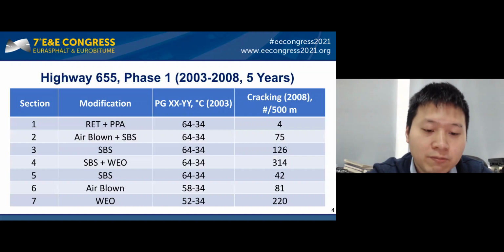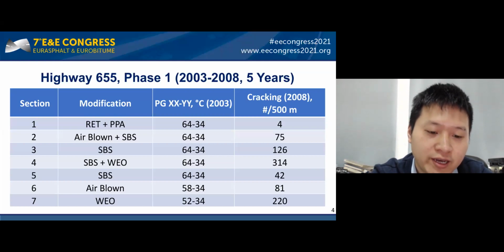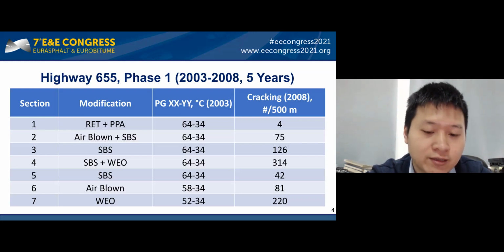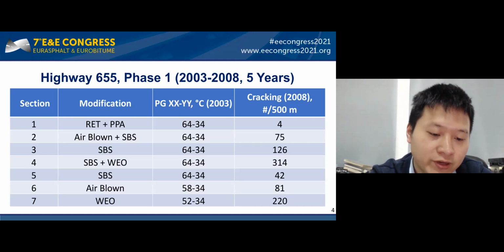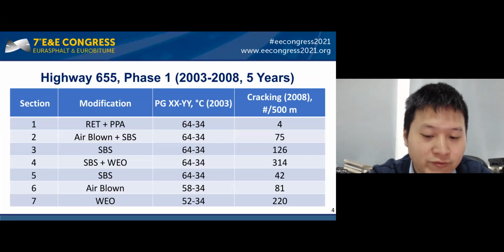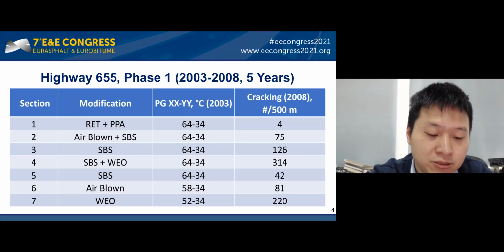Samples tested were original materials as well as binders recovered from core samples taken after 5, 8, and 15 years of service. The purpose of the trial was to validate and, more importantly, find ways to improve upon the Superpave cracking specifications. So, all sections were constructed with binders of nearly the same continuous low temperature grade, ranging from -35 to -37. A variety of modification types were used to obtain the grades, and even as early as 5 years, this showed up as significant performance differences for ostensibly the same Superpave grades of PG -34.